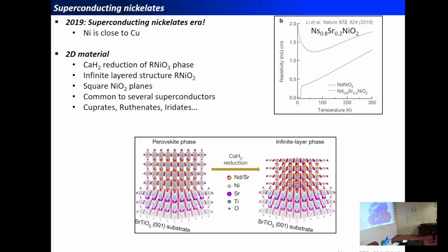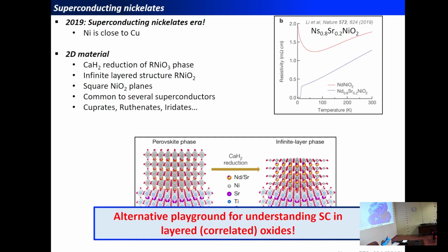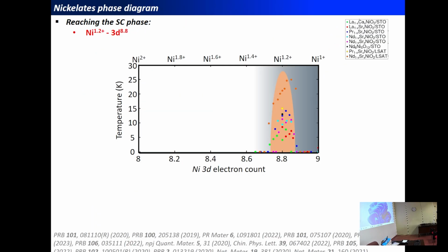So to obtain this infinite layered phase, that's the name of these RNiO2 compounds, you start from a perovskite phase, and through a chemical reduction we remove the apical oxygen just here, and we end up with a planar structure which is made of NiO2 planes separated by rare earth cations. And this infinite layered system based on NiO2 blocks is common to several superconductors such as the cuprates, for instance, the ruthenates, the iridates. And therefore they are really interesting because they are an alternative playground to understand superconducting mechanism in layered and correlated oxides, since we have to deal with 3d transition metal elements.